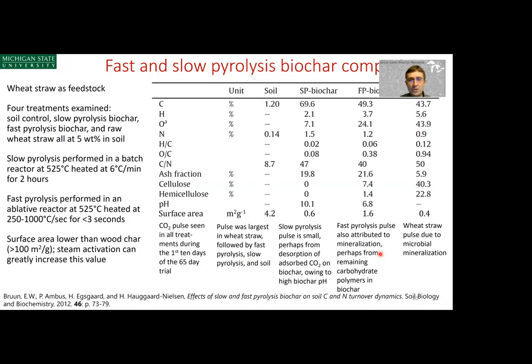The slow pyrolysis biochar was produced under different conditions than the fast pyrolysis biochar. The heating rate was much slower, at 6 degrees Celsius per minute versus 250 to 1,000 degrees Celsius per second. And the heating time was 2 hours for slow pyrolysis versus less than 3 seconds for fast pyrolysis. So then they went through and looked at some of the properties of these different biochars and compared them.